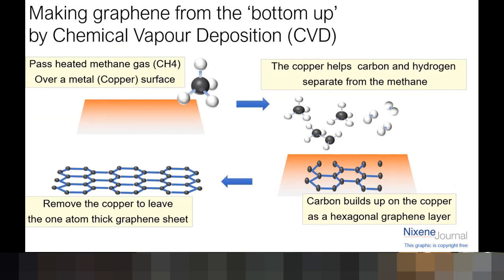So I talked about sheet graphene being made on metal foil. This is how it works. You basically get hot gas, methane, carbon with 4 hydrogens on it, get it very hot, bring it down to the surface of a metal like copper, which acts as a catalyst. The hydrogens pull off and come off as hydrogen gas, and then the carbon atoms land on the surface, and they connect up in the lowest energy shape that they can, and that turns out to be graphene, this chicken wire. And then when the surface of the metal is covered, the reaction stops. Then you peel the graphene off or dissolve the copper away, and that leaves you with a 1 atom thick graphene sheet. That's called the chemical vapor deposition method, and this is a way of making large scale sheets of graphene.